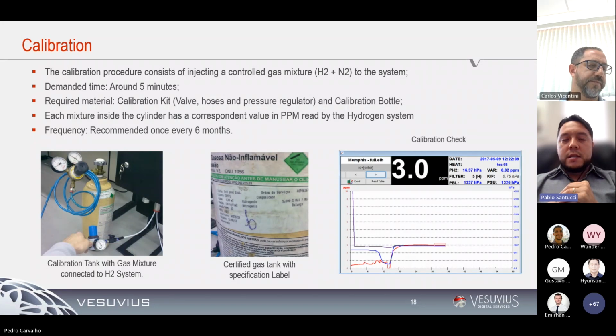In addition to that, we consider calibration gas for running this calibration procedure, which is a mixture of gas considering X amount of hydrogen in nitrogen balance. For example, in this case, as you can see in the graph, 3.0 ppm dissolved hydrogen in steel means that our calibration gas used for reaching that number 3.0 was 1.5% of hydrogen in a nitrogen balance bottle. So that's what the theory says in terms of reference for calibration.